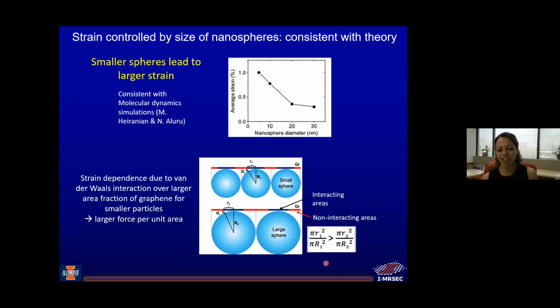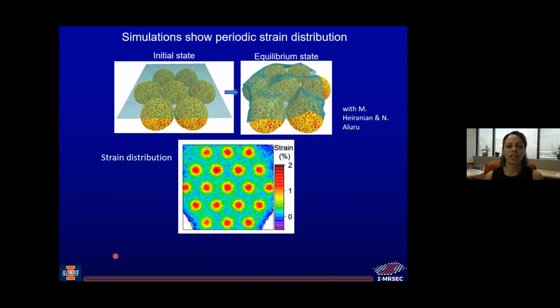And you can look at this ratio and it fits. I mean, that's why you see this kind of quadratic type curve. Okay, so this fits exactly what we expect. But it also was a mechanism that had not been thought about before. No one had actually thought about how it conforms. If you thought about it in the most basic sense, it seems like the strain wouldn't depend on the curvature, but it does if you look at average strain. And this is a way to control strain and also to understand its behavior on these sort of nanospheres. Okay, so that's something that tells us about how to control global strain in graphene.